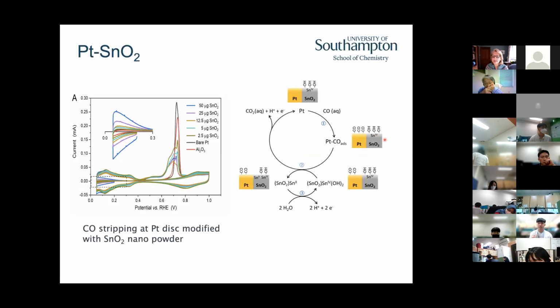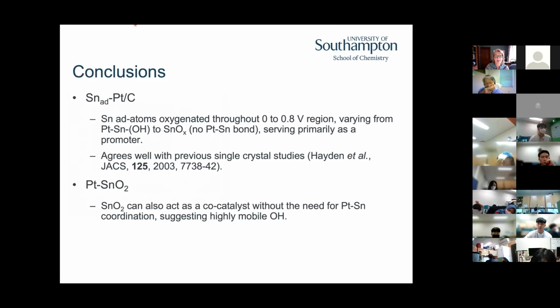And what these data suggest is that you don't need the alloy, right? That as long as the tin oxide remains in good contact with the platinum particles, you will still enhance your catalysis. All right, so I'm not going to go through the conclusions here because I pretty much stated them as I've gone along.